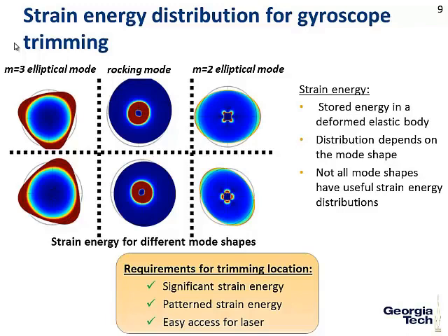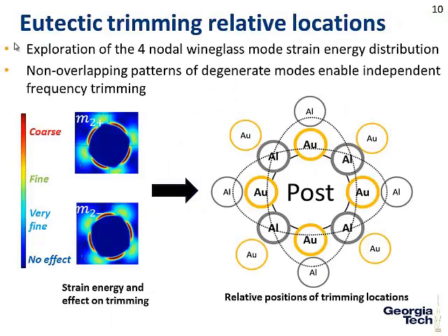Now, if you look at the M=2, it's a bit different. You have strain energy at the bottom, which is very easy access for the laser, but it's also patterned. This is a close-up view of the strain energy pattern at the post. You can see that we have red colors up to blue colors, and these actually are the strain energy. If you do any modification here, you can have more effect than if you did any modification of the stiffness at this location, for example. But also, if you look, this is the pattern of the strain energy for the high frequency mode, and this is for the low frequency mode.